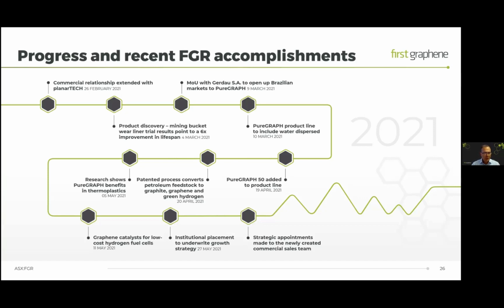In early May, we had some really nice results. We have a collaboration with Professor Tony McNally at the University of Warwick, and he's working with PureGraph as an additive in thermoplastics, and he's reported that it's an excellent additive for thermoplastics, it's very easy to use, and that we can get very high master batch concentrations, and that was reported in May. And then shortly after, we reported the collaboration with Manchester Metropolitan, where they showed that the metal oxide decorated graphenes are effective catalysts in low-cost hydrogen fuel cells.